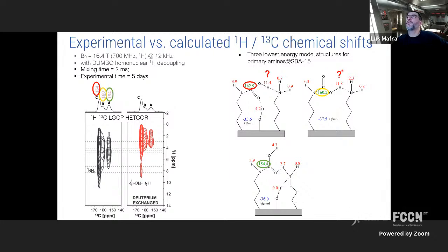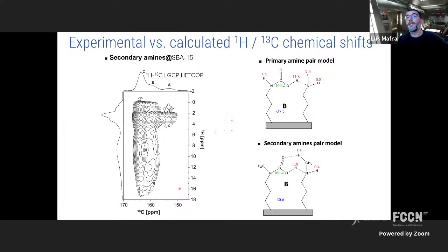So there is still an intriguing problem here: we can compute this 11.4, about 12 ppm proton chemical shift, that is typically a proton engaged in a strong hydrogen bond with a neighbor amine. But we could not find a chemical shift about 12, as you can see here, for a primary amine. So then we tried a two-dimensional spectrum of a secondary amine, and we can see now we have a peak at 12 ppm. So somehow this is something we can still not explain. Why in hell do only secondary amines produce these very strong hydrogen bonds with neighboring amines? There is no other way to produce this 12 ppm peak. Okay, we must have another neighboring amine. At least this is an unequivocal proof that you have pairs of amines interacting, which is fun.